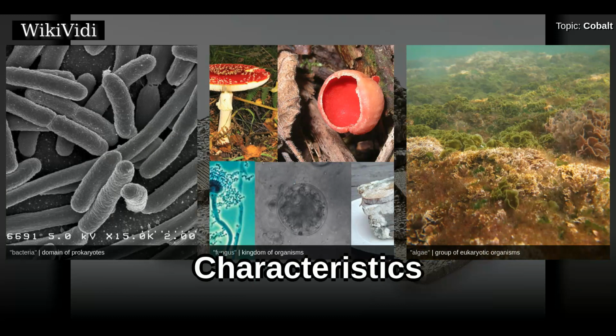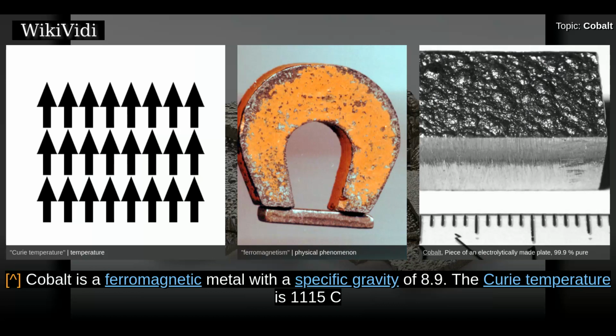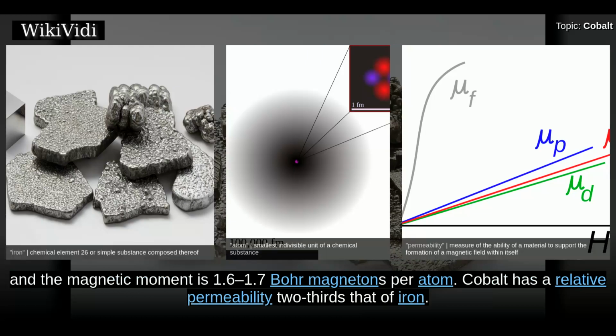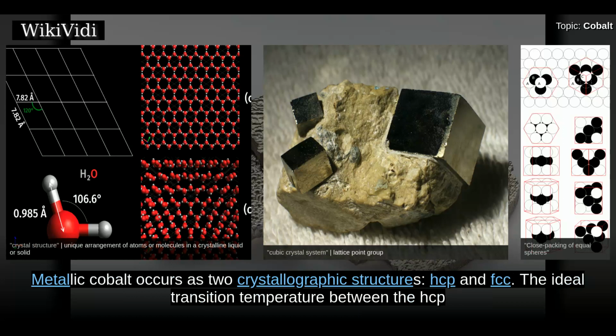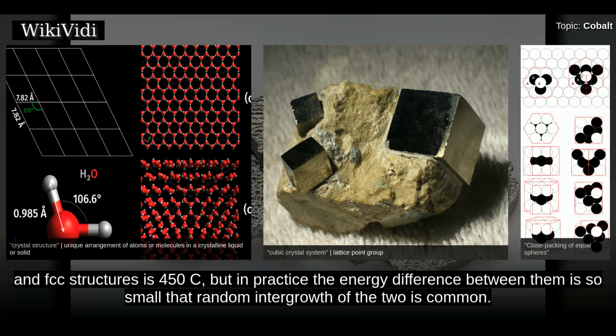Characteristics. Cobalt is a ferromagnetic metal with a specific gravity of 8.9. The Curie temperature is 1115 °C, and the magnetic moment is 1.6–1.7 Bohr magnetons per atom. Cobalt has a relative permeability two-thirds that of iron. Metallic cobalt occurs as two crystallographic structures, HCP and FCC. The ideal transition temperature between the HCP and FCC structures is 450 °C, but in practice the energy difference between them is so small that random intergrowth of the two is common.